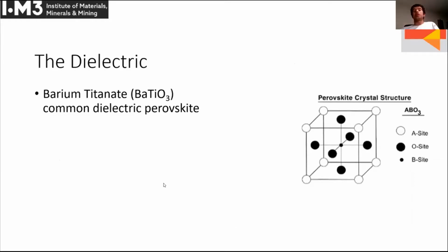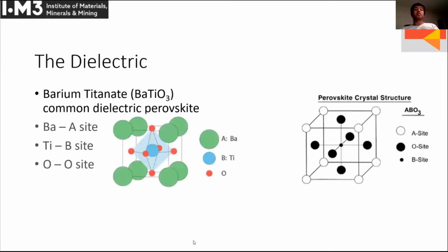Barium titanate adopts what we call the perovskite crystal structure, which is shown on the right here. Each of the spheres represents an atom. So this is very small. A unit cell, which is what we call this, you stack a lot of these next to each other, and these make up your bulk material, essentially. So in barium titanate, barium occupies your corner atoms, titanium occupies the middle of the cube in the center, and the oxygen occupies the 6 center faces of the cube.